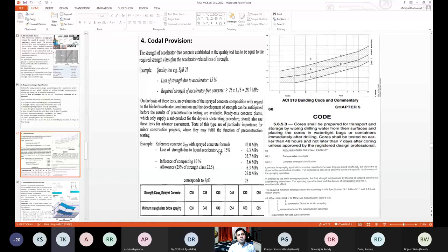It should be achieved. Then this is the J1, J2 which we have earlier discussed, and this is about the ACI 318 code, which states that if 40 MPa is the grade of shotcrete, the cube strength should attain 40 MPa, 0.8 should be attained on cylinder, and 0.84 should be attained in the in situ sample.